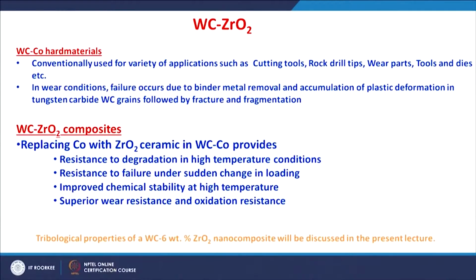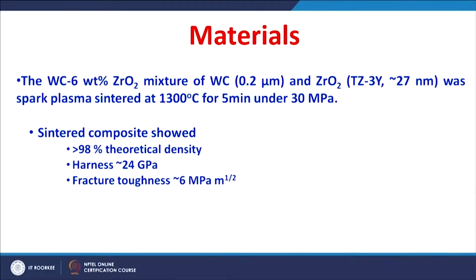But the tribological properties of tungsten carbide zirconia composites are not understood thoroughly. So in this lecture we will see the key results obtained for the tribological behavior of a tungsten carbide 6% zirconia nanoceramic composite. First of all, the tungsten carbide was around 0.2 micrometer, and the zirconia was tetragonal zirconia stabilized by 3 mole percent yttria, with a powder size of around 27 nanometers.